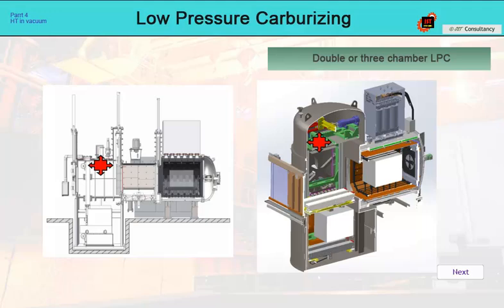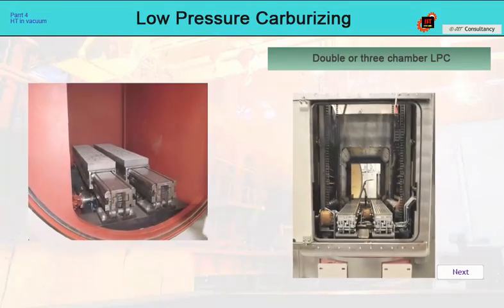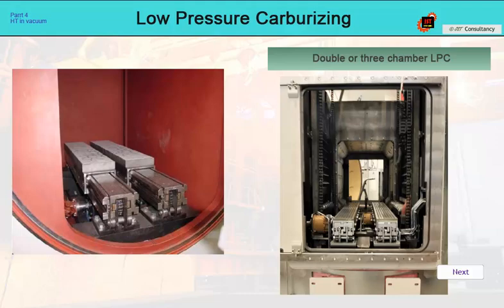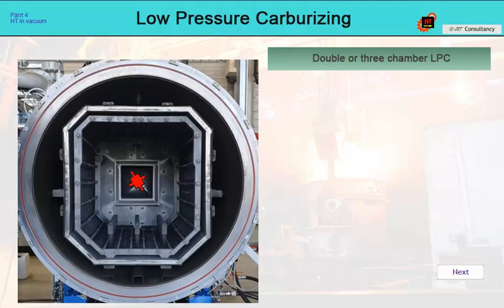In these, currently predominantly two-chamber systems, it is also important that the loading of the clean load into the heating chamber and the handling of the load during oil quenching, including its removal from the furnace, are separated. Otherwise, we will permanently pollute the heating chamber with residual quenching oil clogged by this transport mechanism. The heating chamber should have the possibility of placing a convection fan to improve the uniformity of heating, and the possibility of partial pressure. We must realize that unlike multi-purpose furnaces, these heating chambers can reach temperatures up to 1,250 Celsius, and our processing range can be much wider than before.